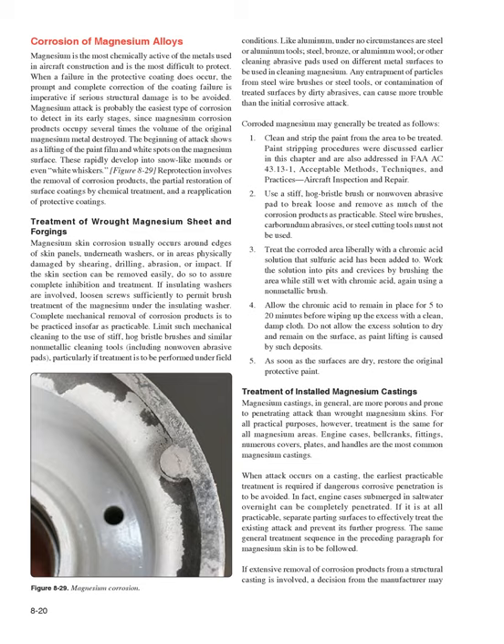Limit such mechanical cleaning to the use of stiff, hog bristle brushes and similar non-metallic cleaning tools, including non-woven abrasive pads, particularly if treatment is to be performed under field conditions. Like aluminum, under no circumstances are steel or aluminum tools, steel, bronze, or aluminum wool, or other cleaning abrasive pads used on different metal surfaces to be used in cleaning magnesium. Any entrapment of particles from steel wire brushes or steel tools, or contamination of treated surfaces by dirty abrasives, can cause more trouble than the initial corrosive attack. Corroded magnesium may generally be treated as follows.